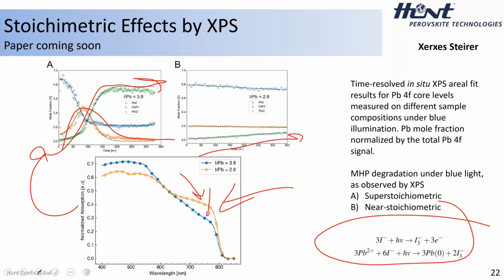We're consuming it by this photo-mediated reaction, but then further converting the lead into lead zero, making this a far more difficult reaction to reverse. In this particular environment, you would call this irreversible.